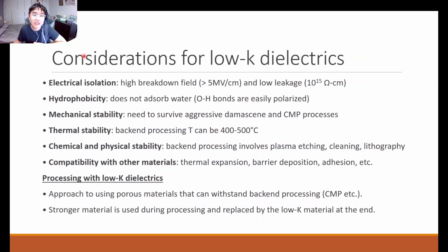So there are certain considerations as for what low-K dielectrics we can actually use in our device. The first one is that fundamentally your dielectric layer exists as an electrically isolating layer. Its main function is to electrically isolate your metal interconnect. So it needs to have a high breakdown field and a low leakage current. And in addition, it also shouldn't absorb water. So it should have a high hydrophobicity and should not be hygroscopic at all, because when water is adsorbed, the OH bonds in water greatly increases the dielectric constant of the material due to the high polarizability of your OH bonds.